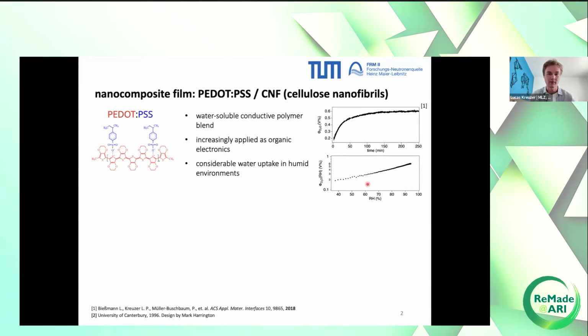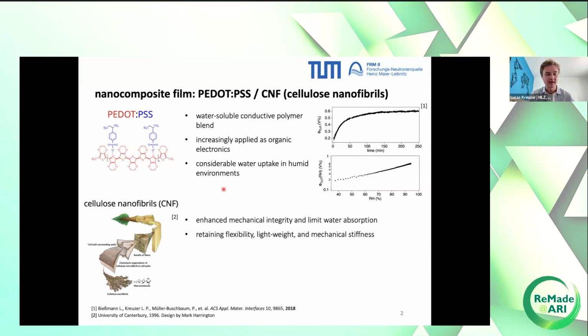An idea we had to overcome this is to blend it together with cellulose. We use a special type of cellulose, cellulose nanofibrils, abbreviated CNF. These are fibers, very long in the micrometer range, but very thin, 5 to 10 nanometers. That's why we call them nanofibrils. These fibers are known to enhance the mechanical integrity and to limit water absorption of a polymer film, for example a PEDOT:PSS film, while at the same time keeping all the good properties like flexibility, light weight, mechanical stiffness, and so on.